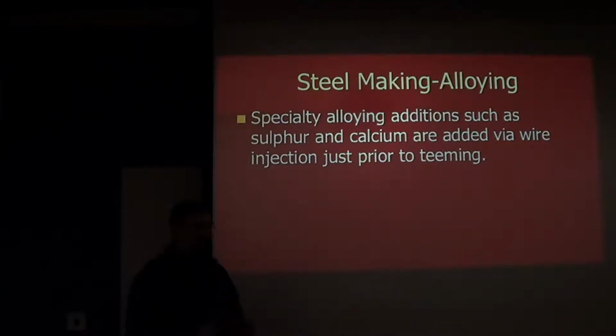and we do. We typically don't want a lot of sulfur, but there are some exceptions. So if you're in one of those exceptions, the mill has methods for putting the sulfur back in to get to the target level. Calcium is an additive that's used once in a while to help manage the shape of sulfides, which can affect mechanical properties. And again, calcium we know is a pretty reactive metal, so we've got to put it in at the end of the process, or it's not going to be really there to do anything for us.